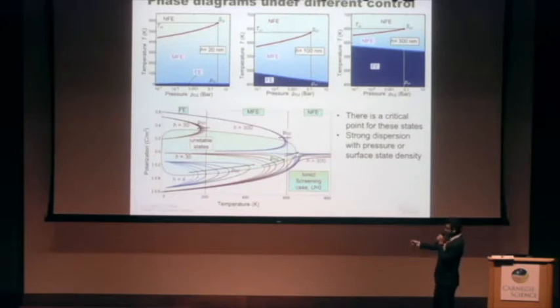So if you look at this particular diagram, in this case a 30 nanometer film, if I change the partial pressure of oxygen, I'm going to change the polarization at a given temperature, and the same thing would apply for fields. And so it's possible that by incorporating this changed boundary condition, we can start to explain some anomalous features that we've seen in local experiments with piezoresponse force microscopy.